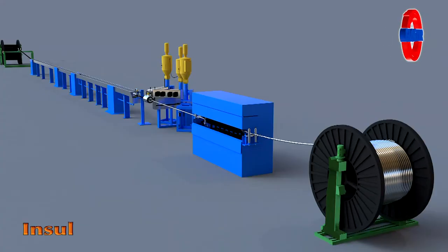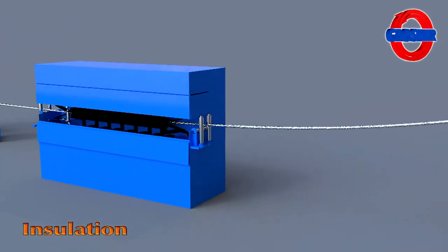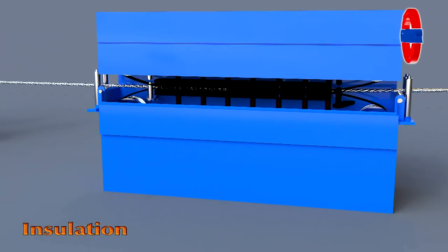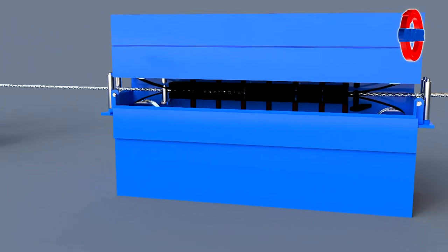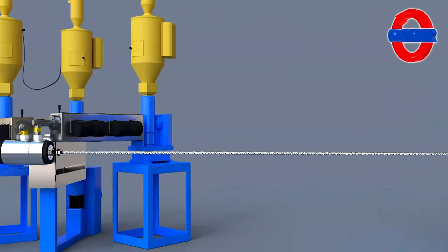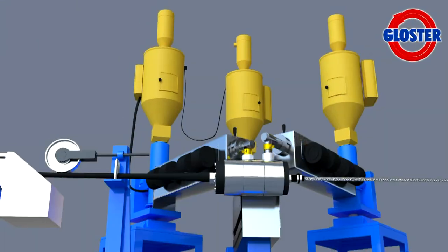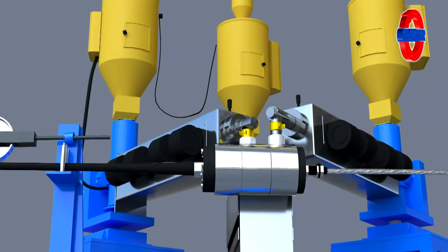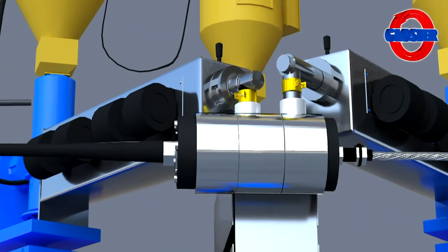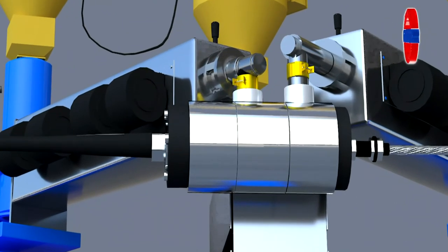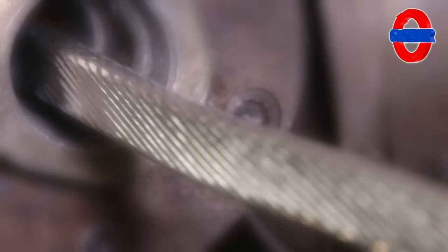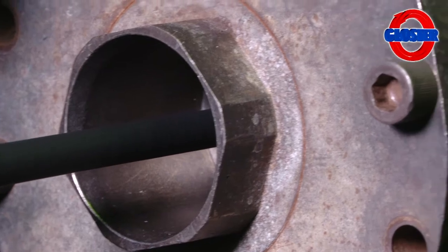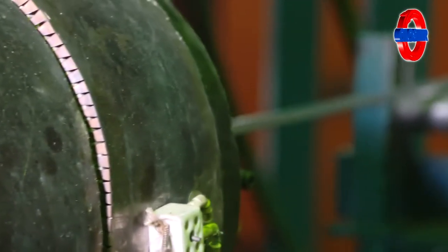For insulation, high-quality XLPE insulating compound of natural color is used on the conductor. It is chemically cross-linked by Sioplas process. The extrusion route with filtered air inlets and a positive air pressurized closed system ensures the insulation process is completely free from impurities and imperfections.